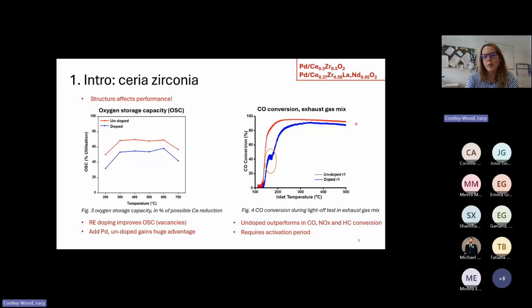However, the doped material and the undoped material are structurally very similar, where they both stabilize in the same cubic phase. They both have very similar surface areas and they both have very similar crystallite sizes. So the difference in the two must be in between the ceria zirconia itself and its interaction with the palladium.